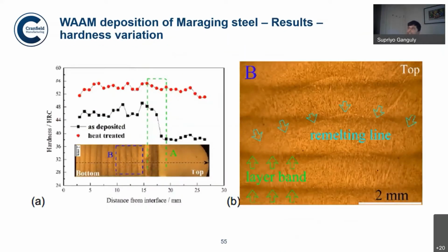Now the interesting thing in maraging steel is that, as you can see, as we keep on depositing, we are aging the steel basically. The deposits done at the beginning are aged slowly by the layers deposited later. The black curve shows that near the top the hardness is quite low, whereas after a certain level the hardness jumps up. But this is an incomplete aging. It is not a full-blown aging.